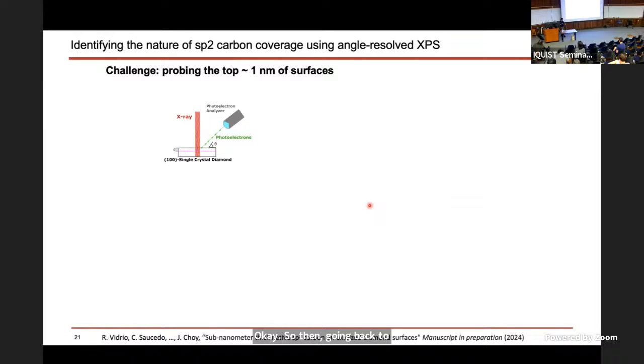Okay, so then going back to this observation that basically no matter what we do, for all of our oxygen treated samples, we see a good amount of sp2 carbon coverage. And so we wanted to study that further, but the challenge is that it's really difficult to probe the top nanometer of any material with conventional techniques. As an example, this is an illustration of our normal XPS configuration. You send in an X-ray, it penetrates pretty much through the diamond, and you have this collection at some angle, and you're collecting over at least several nanometers of the material.